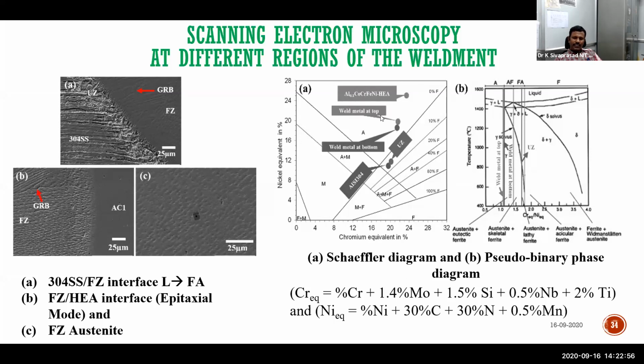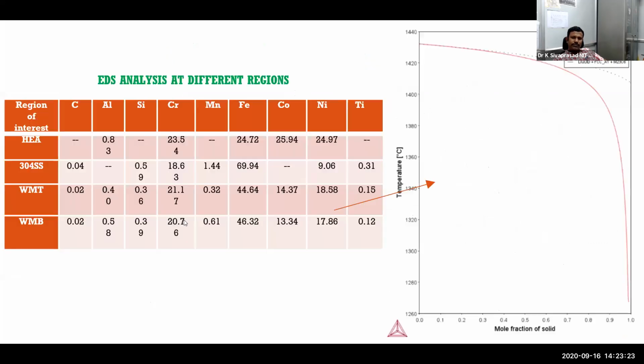Okay, single phase FCC. Whereas in the unmixed zone, one line was formed very close to the fusion zone, and there a small amount of BCC phase possibility was observed, and even our 304 steel whatever we have taken is also not in fully annealed condition. So there also a small fraction of BCC was observed. So that's what the Schaeffler diagram clearly indicates, the superimposed Schaeffler diagram with chromium equivalent. Again, here also we have done calculation of phase diagrams, and we confirmed that similar to TIG welding, here also it is forming only single phase FCC structure.